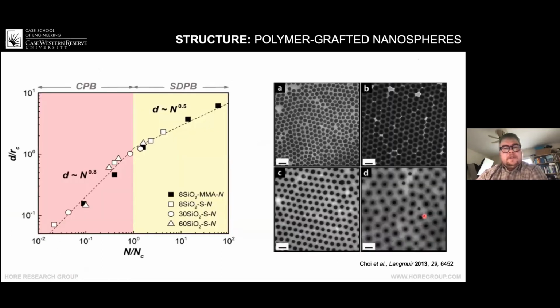So people have done this before, and one of the easiest ways to identify this behavior is not to do neutron scattering, but to prepare many different molecular weights of polymer grafted nanoparticles and just measure what their hydrodynamic radius or hydrodynamic diameter is. And you will observe that the diameter of the particle scales as n to the 0.8 power up until some cutoff distance and then transitions to n to the 0.5 power. So out in this region, in the semi-dilute region, the polymer chains are more ideal. But closer to the polymer core, this 0.8 power is implying that the chains are more stretched close to the core.